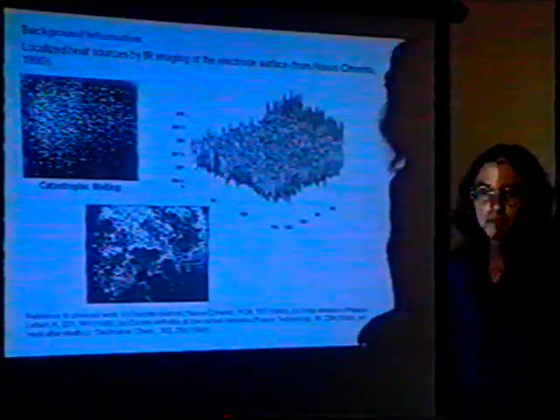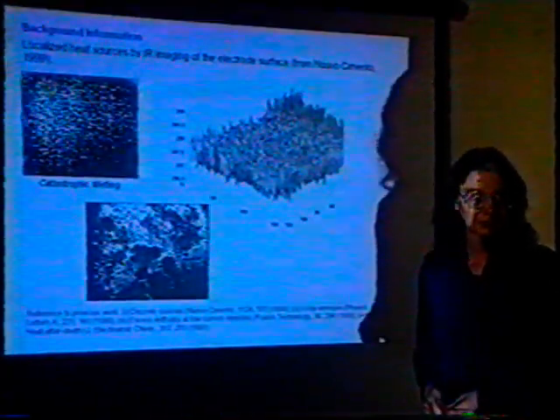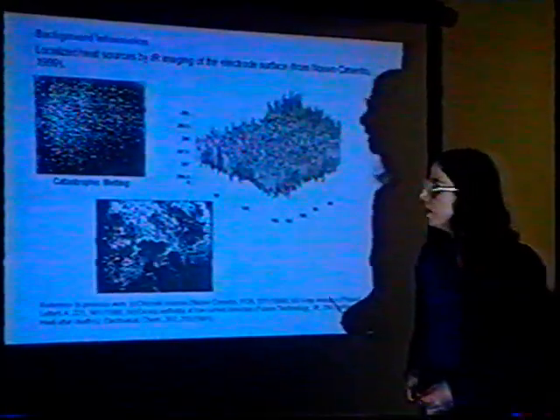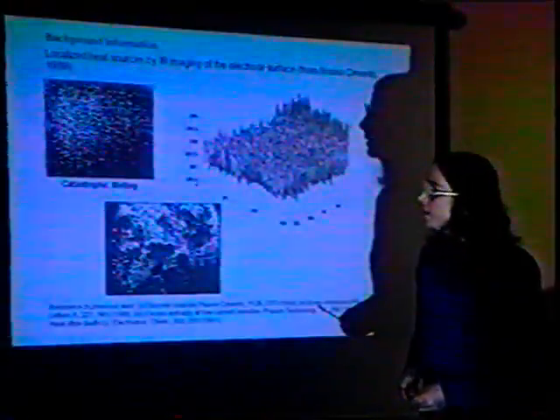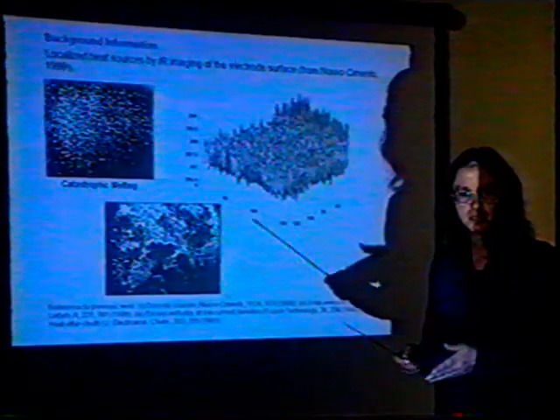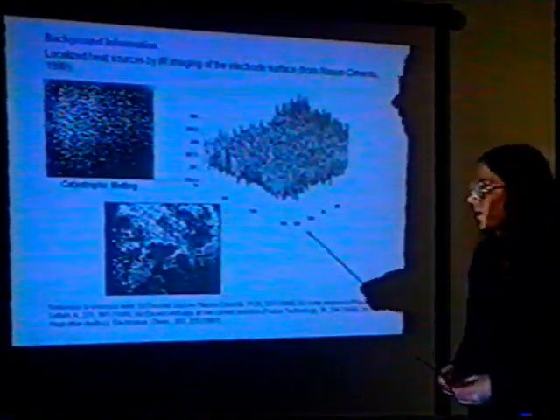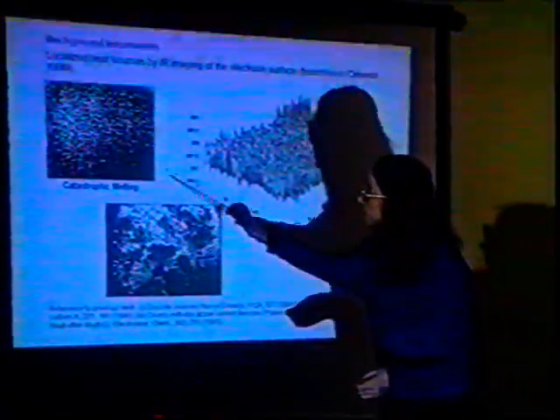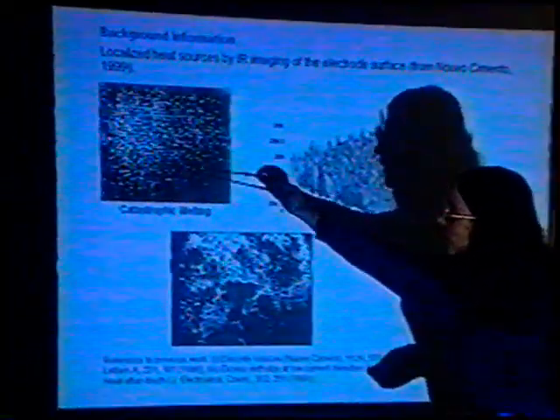What we have done is infrared imaging of the electrode during the co-deposition process. In these experiments, we take a nickel mesh electrode, put it very close to the cell wall, and image it using an IR camera. Here, if you look perpendicularly, you see the distribution of the hot spots. They are of very short time duration. If you view it from the parallel, you see the temperature gradient. The temperature gradient is very steep, telling us that the heat source is very intense and that it is located close to the contact surface.